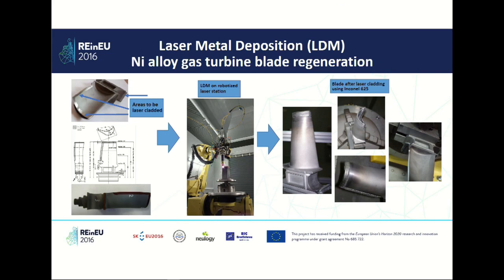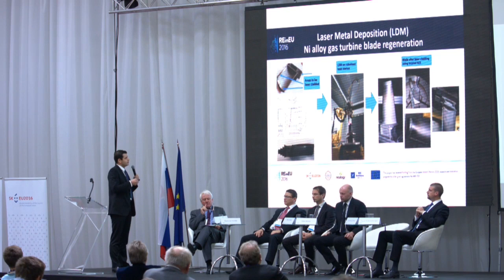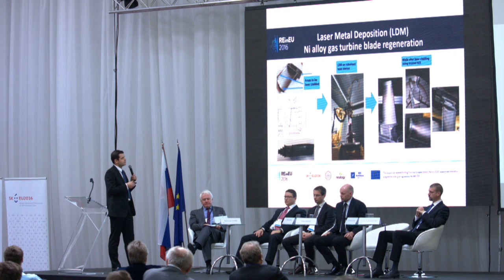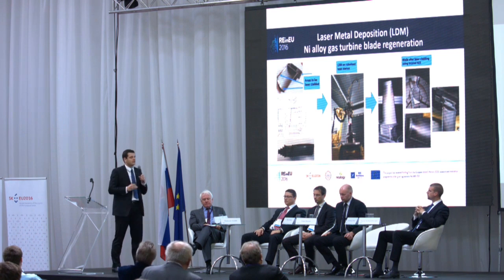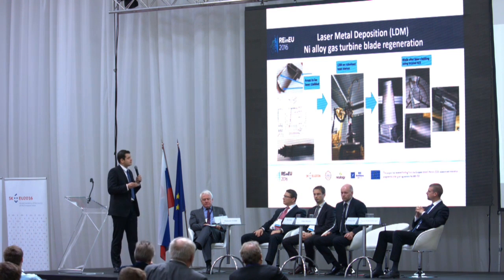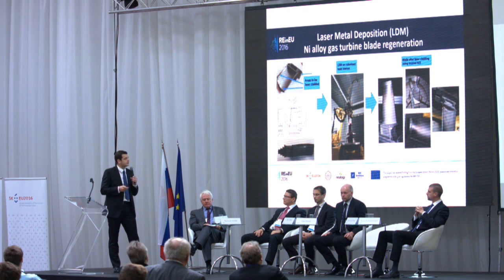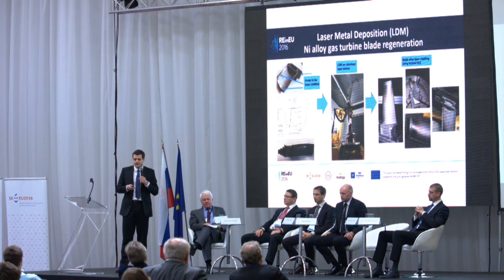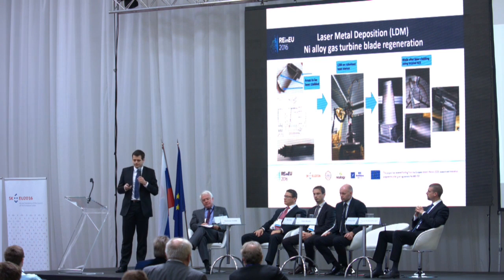Here you can see the surfaces that were prepared for the cladding. Three surfaces. The base material was Inconel alloy. We used our robotization to clad these surfaces with Inconel 625, so you can build up the worn areas of the component, and then just simply by conventional milling you can have a proper part and you can reuse it in the machine.